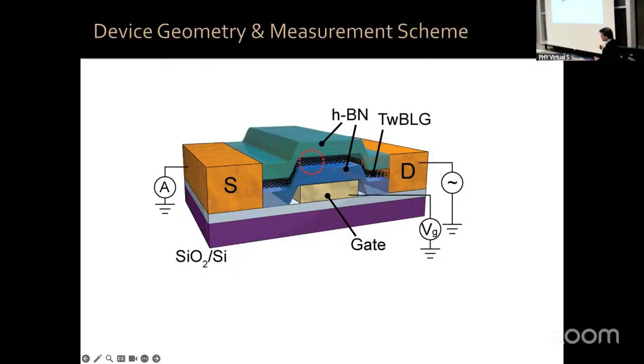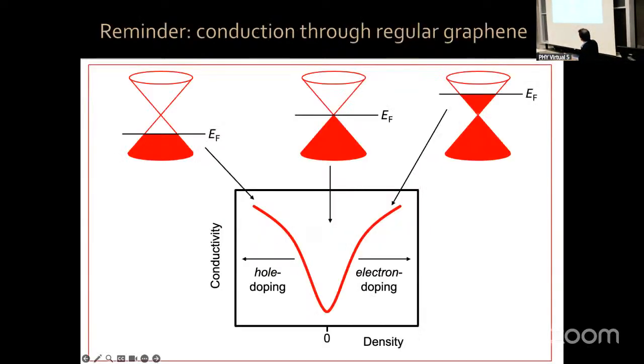So before I show you data on magic angle twisted bilayer graphene, let me show you what happens when you measure just a regular graphene field effect transistor. If you measure the conductivity of just one layer of graphene versus charge density, you have this V-shaped conductivity. If your Fermi energy is deep in your valence band, you have lots of holes, so your graphene conducts very well. If your Fermi energy is deep into your conduction band, you have lots of electrons, so your graphene conducts very well.